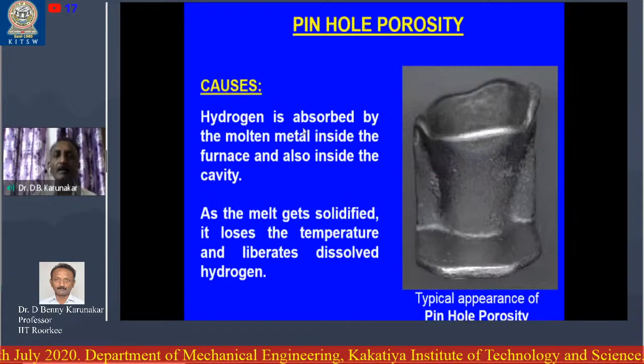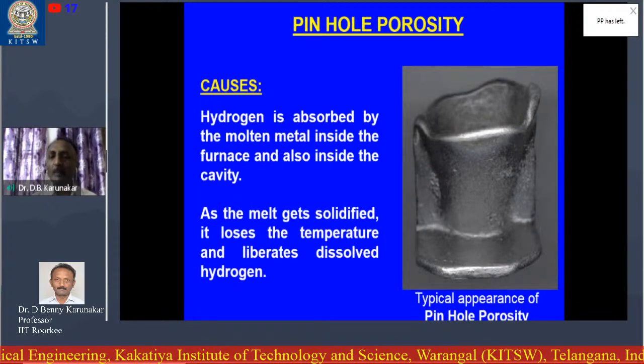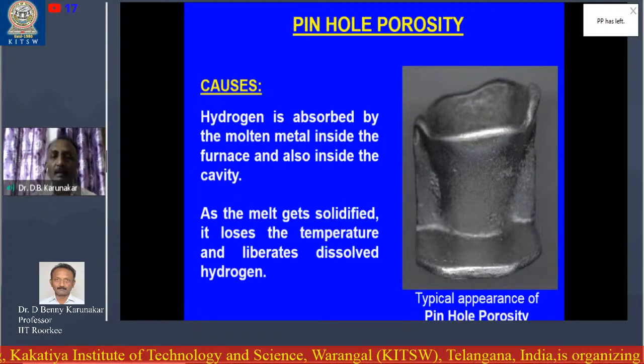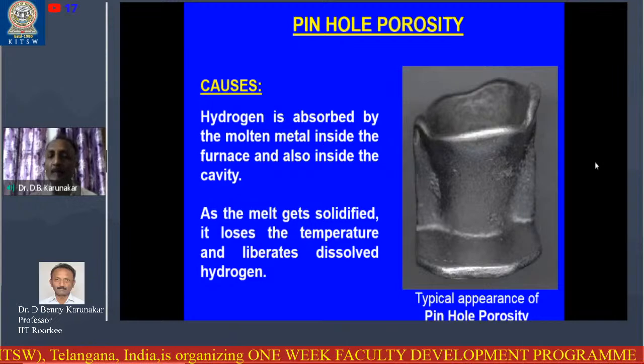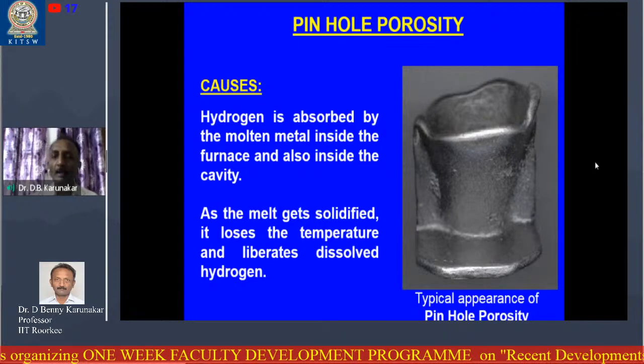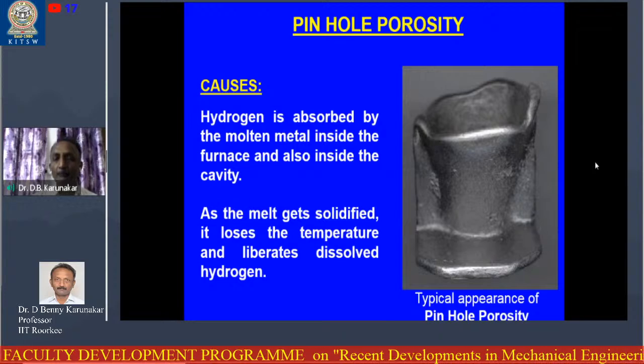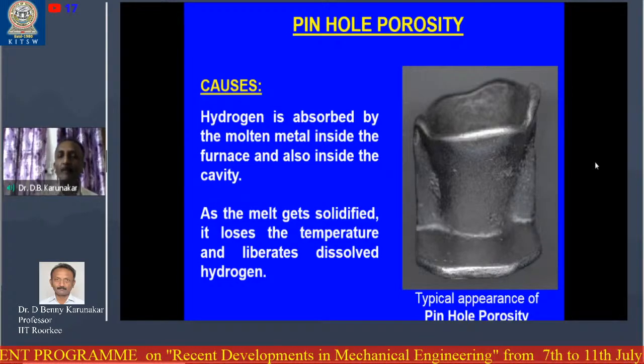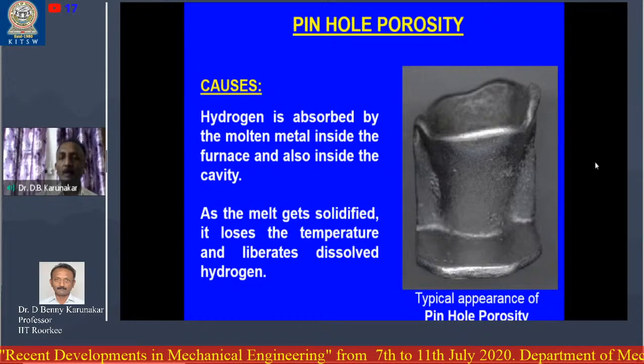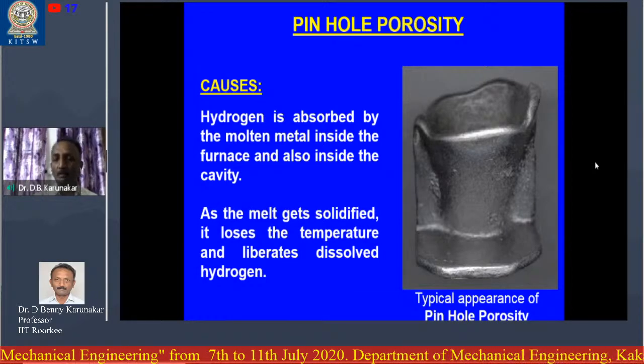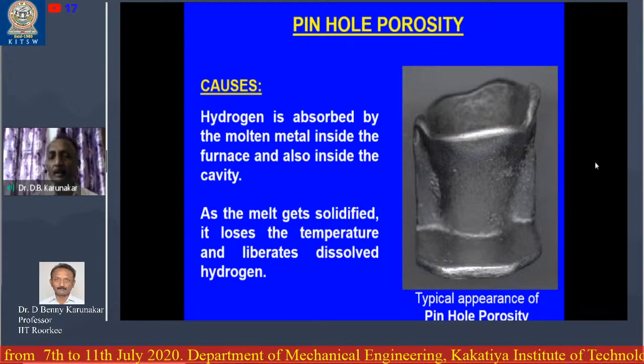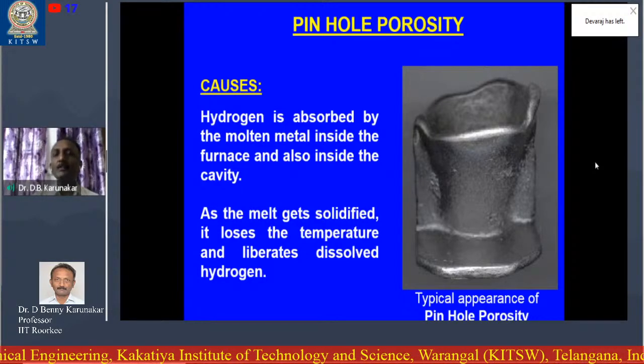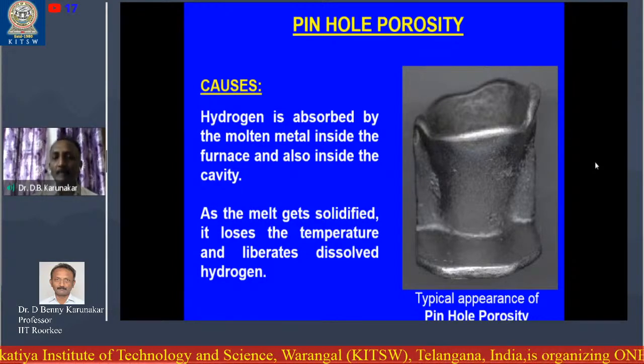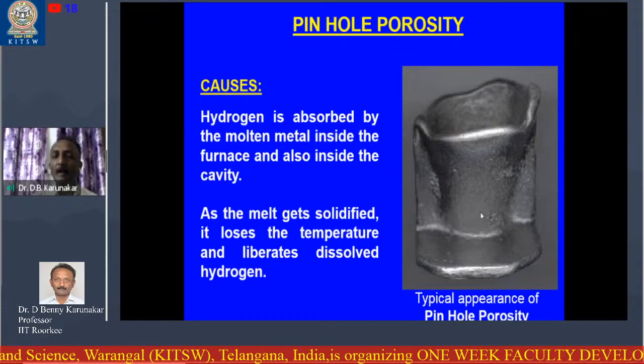The reason is hydrogen is the responsible element for the pinhole porosity defect. The molten metal, especially if you consider aluminum alloys, readily absorbs hydrogen. This hydrogen, while melting, is absorbed by the molten metal and comes along with it, and while the hydrogen is still present inside the molten metal, we pour. During solidification, this hydrogen slowly comes out and forms pinhole porosity on the surface of the casting.